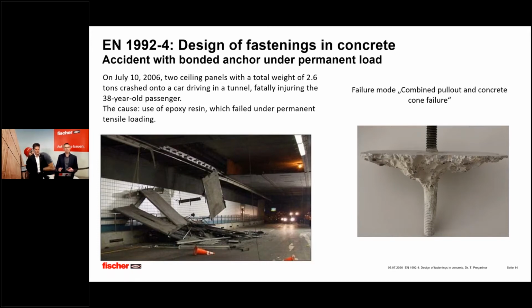Now, if you would install this anchor a bit deeper, or if you would reduce the bond strength due to temperature, for example, then you would get a failure mode which looks pretty much like that, where you get pull-out failure at the bottom of the anchor, and close to the surface there is still a concrete cone failure.